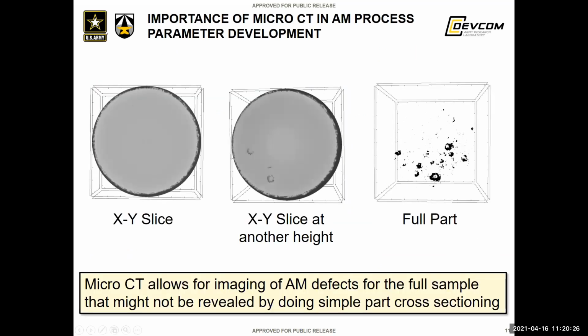And then going on from the powder itself to the final AM process, this is going back to what I was discussing before, the benefits of having CT in addition to optical microscopy characterization of the overall laser processing parameters. This on the left right here is just a single XY slice layer within one of my latest processing parameter developments for high strength steel on the Renishaw. So you can see it looks pretty good, there might be a small defect over here, nothing really big. If I took a single layer like that and just happened to reach that layer when I was optically looking at it, I would think my material was doing great.